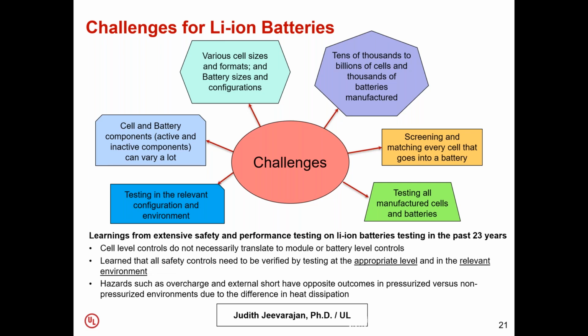And the biggest challenge is to screen and match every cell that goes into building a battery, and also to test all the cells and batteries that are manufactured before they leave the manufacturing facility. And lastly, testing in the relevant configuration and environment is very critical, and it's a big challenge because it is not always possible. But from our extensive safety and performance testing in the past more than 2 decades, we found that the cell level controls do not translate to module or battery level controls. And we also learned that all the safety controls need to be verified by testing at the appropriate level or configuration and in the relevant environment.